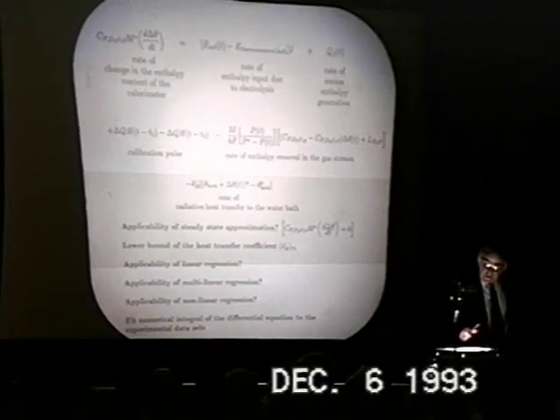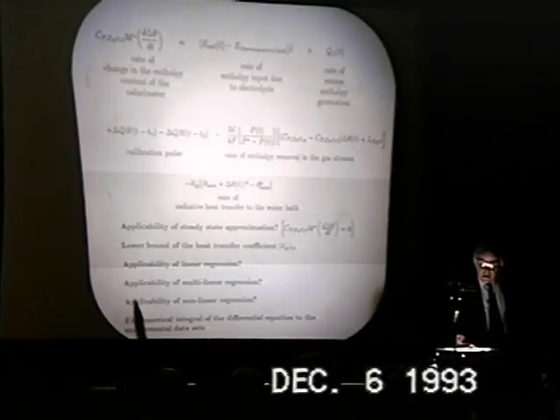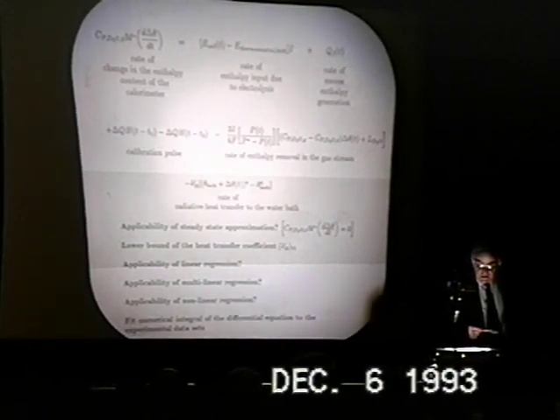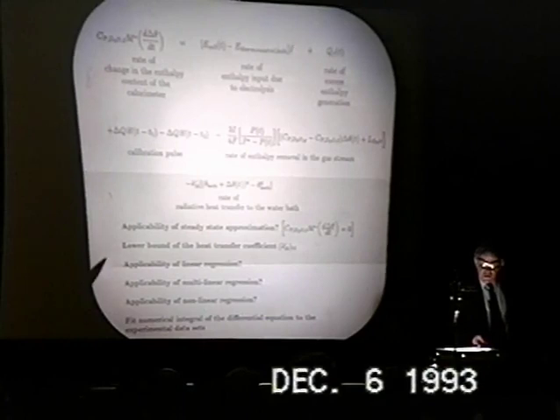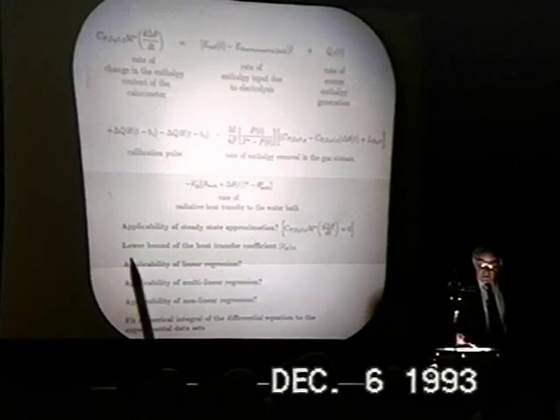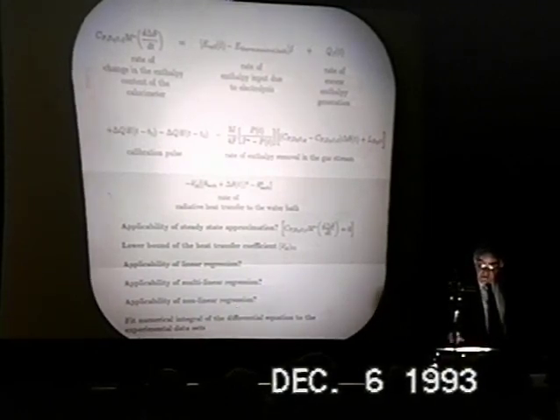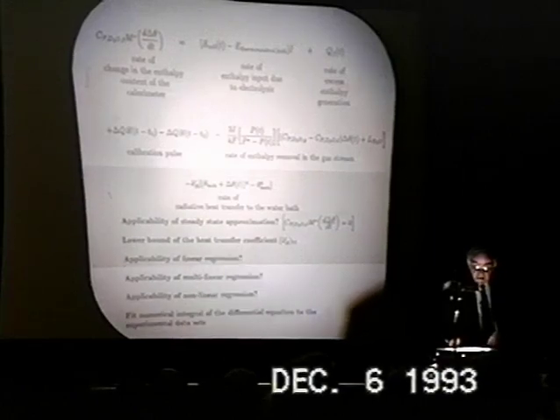Well, in the normal course of events, you will of course look at that as we did in the early years, and then you would ask yourself the question, can I do something about this with linear regression? Can I apply multilinear regression? Or in the most sophisticated way, can we apply non-linear regression? Now, because we were under such intense pressure, we omitted most of these intermediate steps, and we went straight away from the steady state approximation and the lower bound of the heat transfer coefficient to applying non-linear regression. And we actually fitted the numerical integral of this equation, the function equation, to experimental data sets. This is the approach we did.